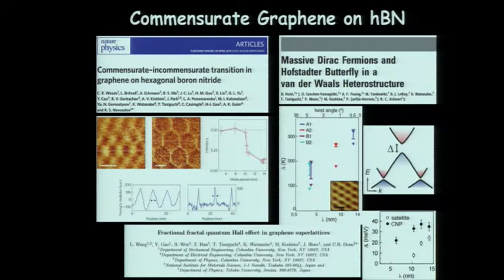And then beyond that, there were transport measurements, which showed the same type of thing where a gap was opening. So this is work from Pablo's group here, looking at very long wavelength. You can start to see band gaps on the order of room temperature, 300 Kelvin. Also from Cory Dean's group, where they see band gaps opening on the order of about the same 25, 30 meV. And so what's happening here in these very long Moiré patterns is there is some evidence that there is a band gap opening. There's some breaking of the symmetry.